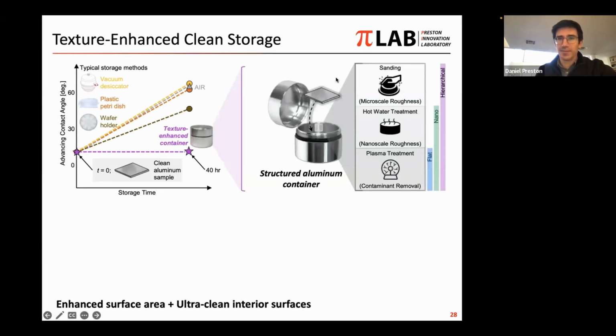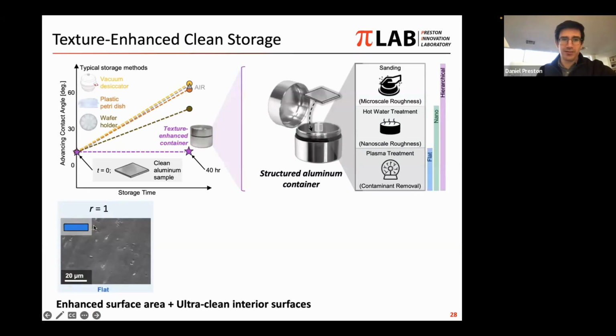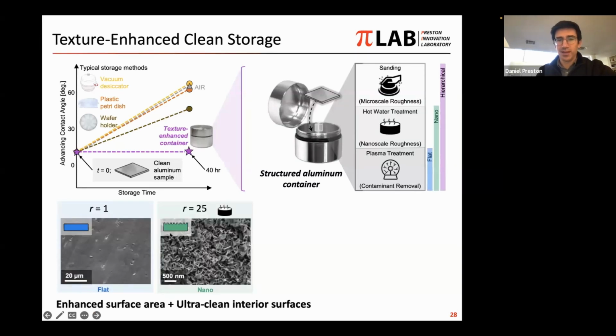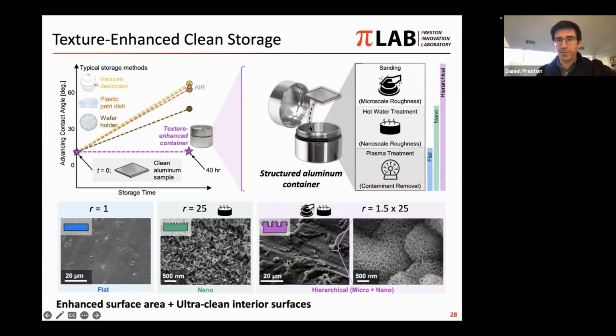Here's the container. We structured the inner wall by either sanding or hot water treatment or both. And then we used plasma treatment. So it would look like either a non-treated flat surface, a surface that we used hot water treatment on, or one that we sanded and then used hot water treatment on. In aluminum, the hot water treatment forms these nice leaf-like nanostructures. And then in all three of these cases, we used the plasma cleaning to make sure that the inner wall of the container was very clean.